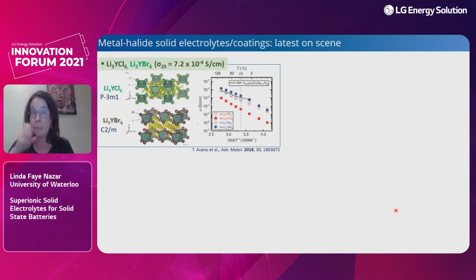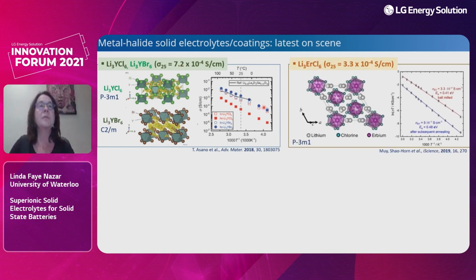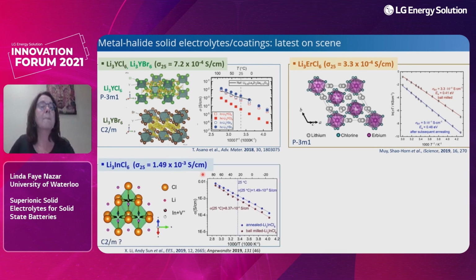So we were not the first, of course, to discover this. I would say that the group at Panasonic was probably the first to report in 2018 that lithium yttrium chloride or lithium yttrium bromide, with modest conductivities, had some pretty interesting properties, followed by a paper of Yang Shao-Horn's on the erbium chloride, again, sort of modest conductivity. And my colleague at the University of Western Ontario, Andy Sun, then reported on lithium indium chloride, now with a significantly higher conductivity and above that benchmark of 1 millisiemens that I mentioned.